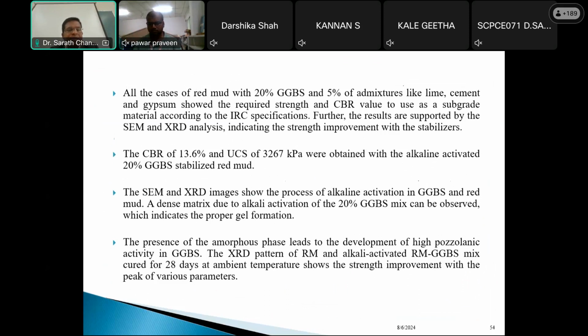The SEM and XRD images show the process of alkaline activation in GGBS and red mud. A dense matrix due to alkaline activation of the 20% GGBS mix can be observed, which indicates proper gel formation. And the presence of the amorphous phase leads to the development of pozzolanic activity in GGBS. The XRD pattern of red mud and alkaline activated red mud GGBS mix cured for 28 days at ambient temperature shows the strength improvement with the peaks of various parameters. And here, as I told you, I'll give you a lot of scope for your work if anyone is interested.